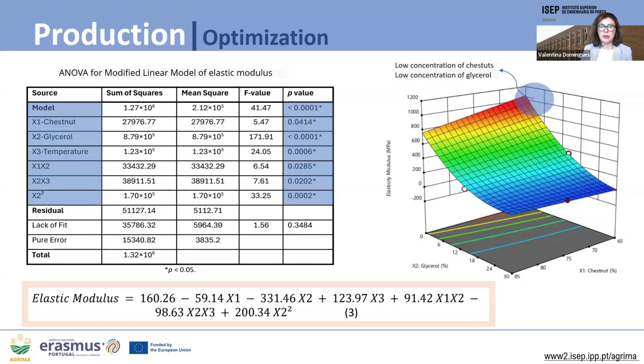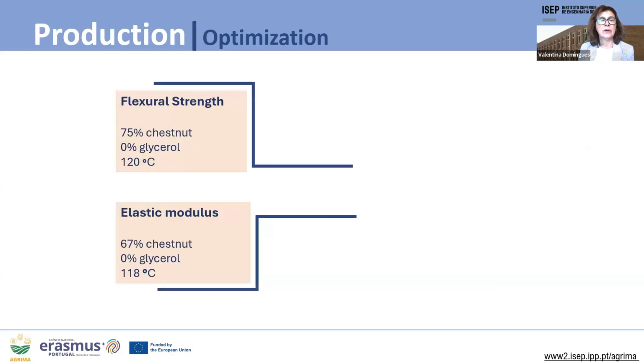Regarding the elastic modulus, the model was optimized by eliminating the irrelevant variables, resulting in this equation, which includes, as you can see, a second-degree interaction. As can be seen in the 3D graph, we have higher elastic modulus with low concentration of chestnut and low concentration of glycerol. So with all this data, we obtained the best composition for the biocomposite.